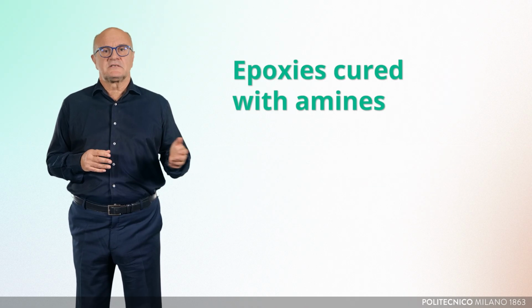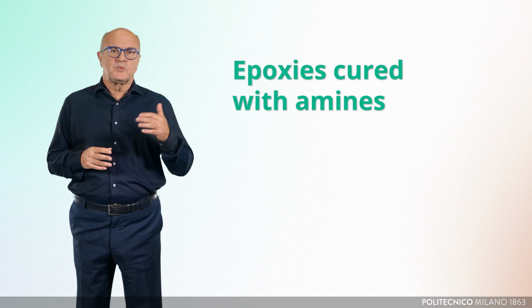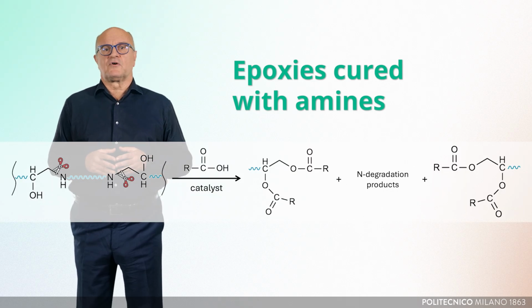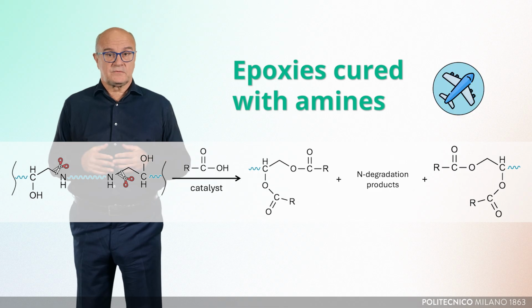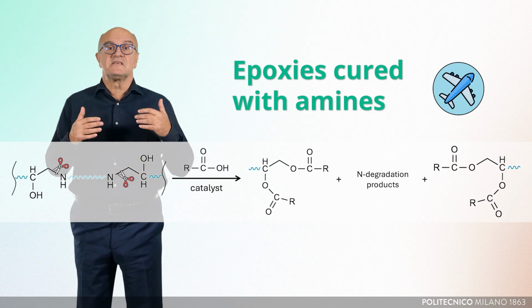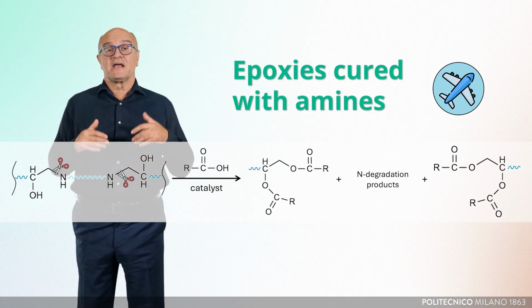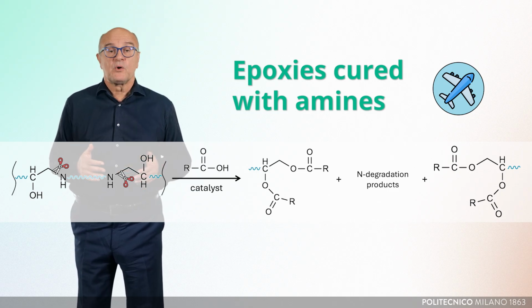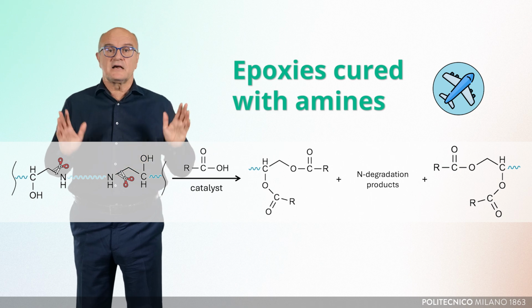Epoxy cured with amines. Epoxy resins, when cured with amines, are commonly used for carbon fiber composite manufacturing, for example, for the aerospace sector. The amine-cured epoxies have very strong covalent carbon-nitrogen bonds, which again can be selectively broken by catalyzed acidolysis with the liberation of clean carbon fibers.